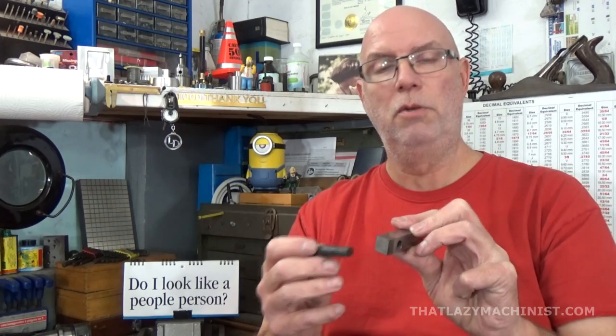Now, that is not much of a problem, and generally we would rough and then finish. But what could I have done here to get that hole almost perfectly parallel? You may have noticed that this electrode is way longer than it needs to be. I cut here, and I stopped the cut when the electrode just came out the bottom side, just barely. But I could have continued on quite a bit, permitting a new surface of the side of the electrode, one that hasn't been slightly worn down, to penetrate the full depth of the part, and that would have ensured a much more parallel hole.